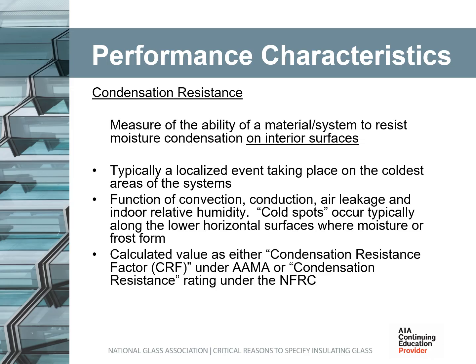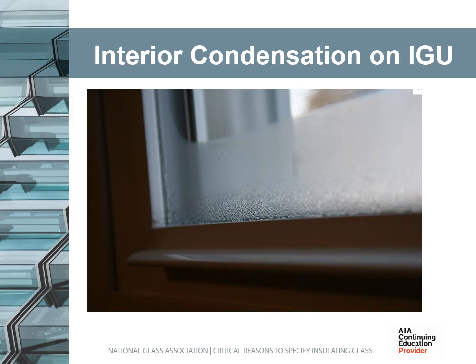resistance to condensation formation. Condensation resistance is typically a localized effect due to thermal conductivity differences of discrete components. A highly conductive material that reaches from the warm side surface to the cold side surface will create a localized heat flux, significantly greater than the lower conductivity insulating materials around it, creating a thermal short circuit. Such thermal short circuits can have a detrimental effect on the ability of a fenestration system to resist moisture condensation. Here's an example of a unit with considerable condensation. In some cases, the impact of such condensation can be so severe that frost and/or ice can form on the interior surfaces of the window. This can lead to a variety of problems, including water damage and poor indoor air quality. Efforts to improve fenestration system performance to improve condensation resistance include optimization of framing materials and thermal breaks, control of air leakage through weather seals and frame joints, and the optimization of the insulating glass unit component.